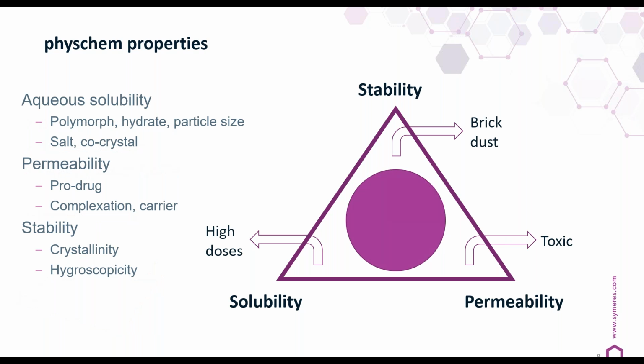Looking at your solubility, you can change your polymorph, you can look at hydrate formation, you can change your particle size. If that doesn't work sufficiently, a salt or co-crystal might give you the purpose. Looking at permeability, you cannot do that much on screening. So you have to change something on your molecule, which means you can have a look at a prodrug, you can have a complexation or carrier.